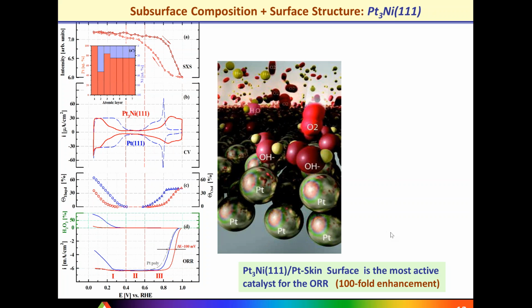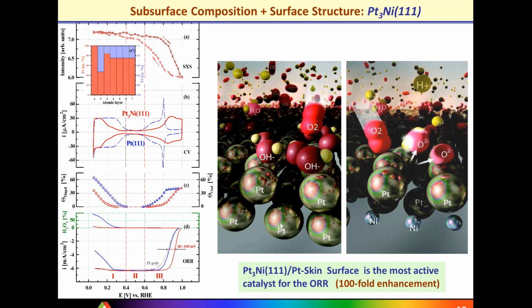So in essence, we were looking into those two cases, one with pure platinum, which was significantly covered with so-called oxygenated species that are coming from water at potentials that are relevant for oxygen reduction reaction, and a case where we have again a pure platinum surface, however the subsurface was nickel, and that nickel was influencing topmost platinum atoms in such a way that the electronic modification of topmost platinum atoms is substantially changed and altered, leading to substantially lower coverage of those oxygenated species, which leaves a substantial amount of free platinum atoms that are capable of adsorption of molecular oxygen. And all of that leads to substantial improvements in catalytic activity.